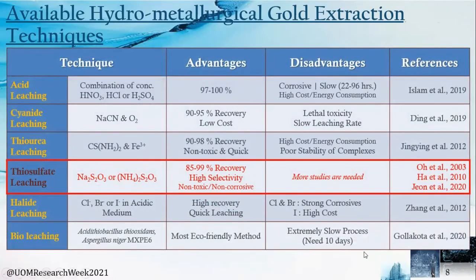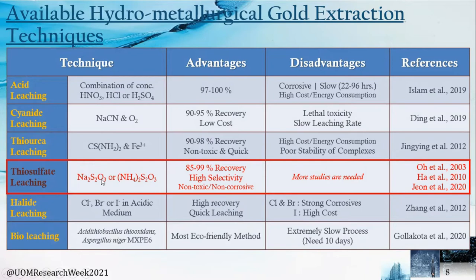In this table, we see several hydrometallurgical approaches for gold extraction from e-waste. Acid leaching, cyanide leaching, and halide leaching are either corrosive or toxic methods. Bio-leaching is a very eco-friendly method, but it is an extremely slow process. Thiourea leaching and thiosulfate leaching are the best alternatives for gold leaching from e-waste. As a method with high selectivity and non-toxic, non-corrosive properties, thiosulfate leaching was selected to study in this process.